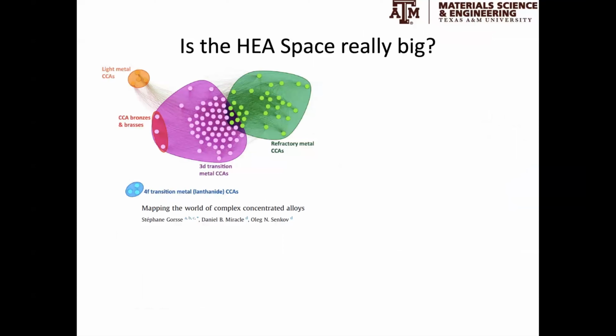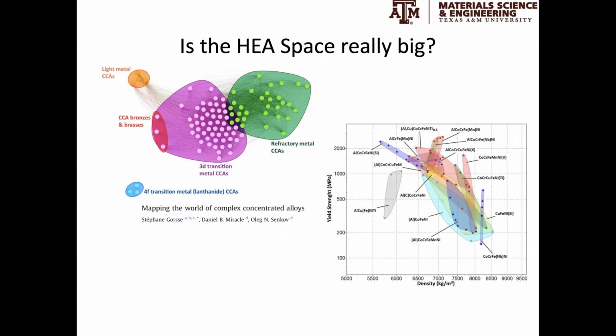So the question that we set out to answer in this work is whether the high entropy alloy space is really big. In fact, some people may argue, like we do, that the entropy effect may not be as important, because phase stability is ultimately the consequence of competition between phases with different Gibbs energies rather than different configurational entropies. We may also argue that the maximum configurational entropy is very difficult to attain before the alloy melts to begin with.